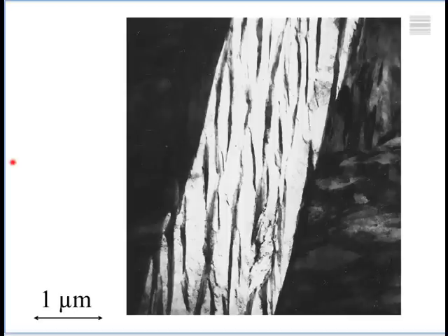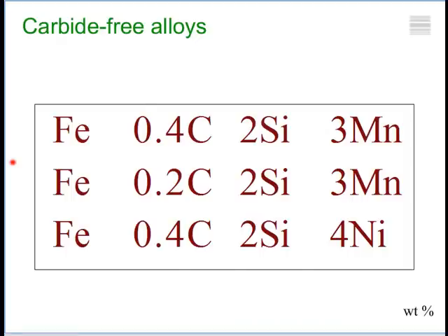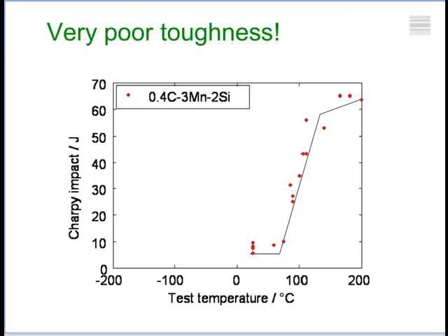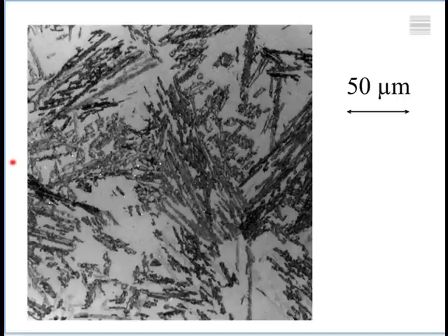But my fundamental question is, why do we have this poor toughness, even though the microstructure is so nice? Yeah. So we have a grain size here, which is effectively a quarter of a micrometer. We have the films of austenite, which are ductile. Then why are we getting such poor toughness? Well, it's actually that T0 curve. If you look at the structure here, we have the bainite, but we also have these very large regions of austenite. And it doesn't matter how long I transform it, I will not get more bainite because the T0 curve limits the amount of bainite that can form.